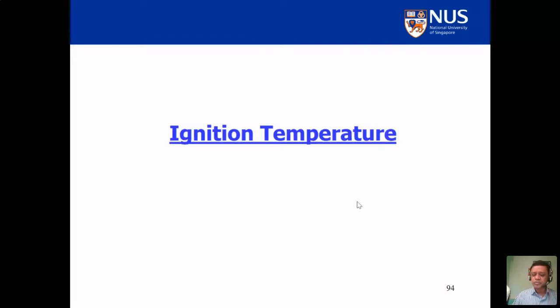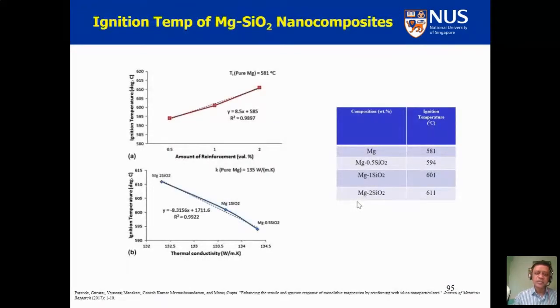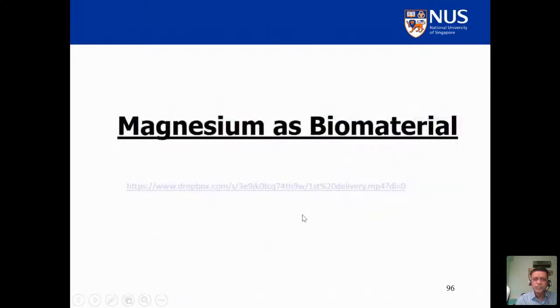Ignition temperature, because of the misconception of the people, so we also tried to investigate how this nanoparticle affects the ignition response of the material. And we found that if you put, for example, silicon dioxide particle, your ignition temperature goes from 580 to 611 degrees centigrade, which is a 30 degrees centigrade increase. Note here that magnesium auto-ignites at 580 degrees centigrade, which is a very high temperature, so it's not an issue. And we realize that this is happening because the thermal conductivity of the base material is reducing, and apparently the reduction in the thermal conductivity is translating quite well with the increase in the ignition temperature.